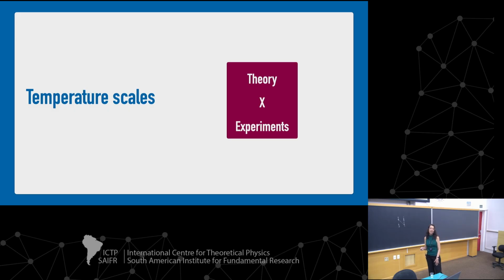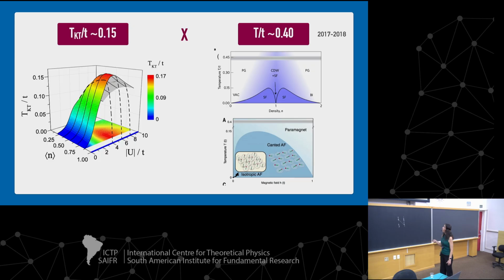So if we look at the temperature scales between theory and experiments, we see here what we found is the highest Kosterlitz-Thouless temperature is around 0.15 in what we call the sweet spot. But in experiments that I've shown in 2017, 2018, it's here, 0.45, 0.40, so kind of 3 times above the critical temperature. So these experiments are not going to see what's going on.